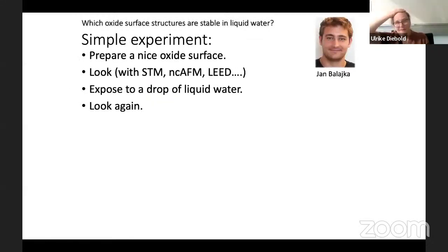So Jan Balajka in my group did his PhD on this. I said, okay, Jan, please stick TiO2 100 and 011 samples in liquid water, prepare a nice surface, look if it's nice, expose it to a drop of liquid water, and then look again and see if the surface structure stayed the same. It turns out that this is not so trivial, because he tried many different times. Of course the water we use is as clean as possible, it's Milli-Q water and outgassed. He tried to do that in a glove box, under a stream of ultra pure argon and things like that. He got different results each time.